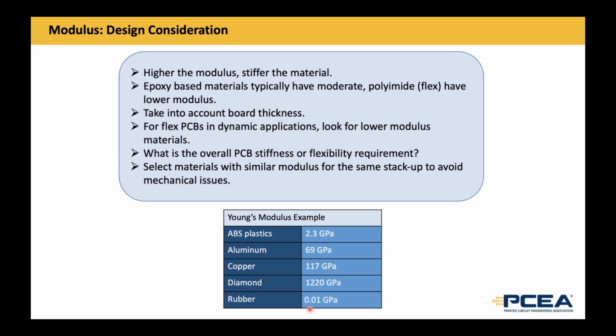What is the overall thickness of your board? So if, for example, you're working on a dynamic flex application where your board is flexing a lot, repeatedly, you would want to look for a lower modulus material. And similar to what I had mentioned in the CTE section, select materials that have similar modulus values to avoid mechanical issues.